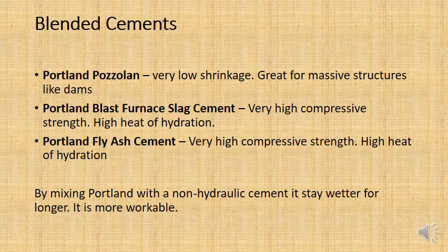concrete that was to be used on top of Mount Corrick, and you made the concrete at the concrete factory in Shoresh, well, it then will take you half an hour to drive the concrete truck to the top of Mount Corrick. And if you were just using regular Portland cement, it's already started to go hard and less workable and turn into a thick sludgy honey by the time you reach the top of the mountain. By mixing it with a blend such as blast furnace slag, it's going to be runnier and wetter for longer, making it more workable, more usable.